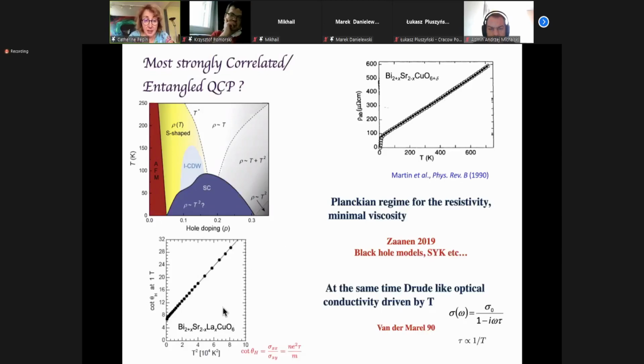Then there was this controversy outlined by Anderson. If you look at the Hall cotangent, sigma xx over sigma xy, for a Fermi liquid it's written like ne tau over m, but then the tau is in T squared. So it seems as if you have two lifetimes, one lifetime going like 1 over T, and one lifetime for the electron going like 1 over T squared. This is a conundrum for cuprates. This was kind of an unsolvable mystery of condensed matter, maybe tougher than the pseudogap, because with transport it's notoriously difficult to beat the T squared for conductivity.